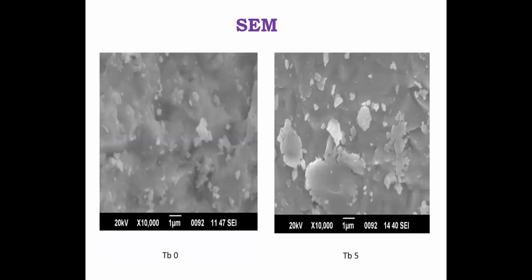Surface morphology of the samples was analyzed using the scanning electron microscopic images shown here. Differently shaped particles are seen in the images, and agglomeration of particles is also evident from these images. So the incorporation of terbium ions may promote particle aggregation and the growth of irregular crystalline grains. So we can say that the doped sample exhibits more irregular shape and size as compared to the pure sample.